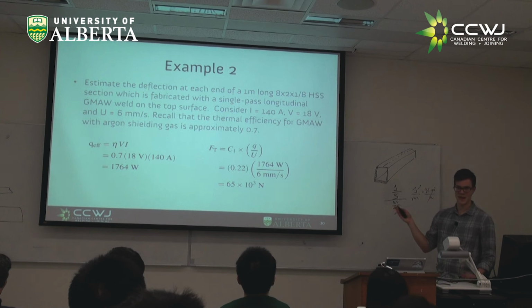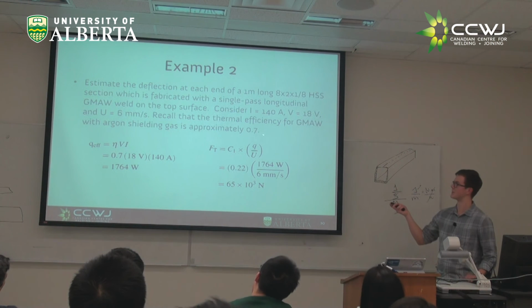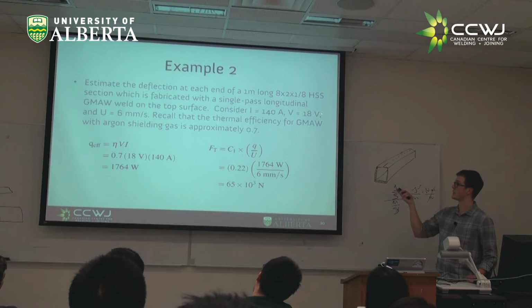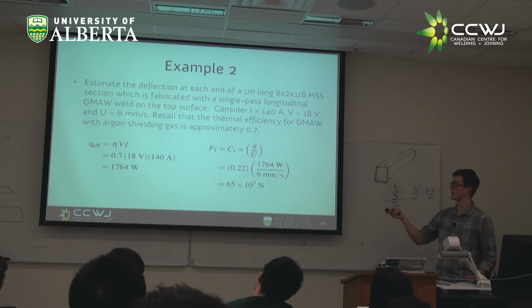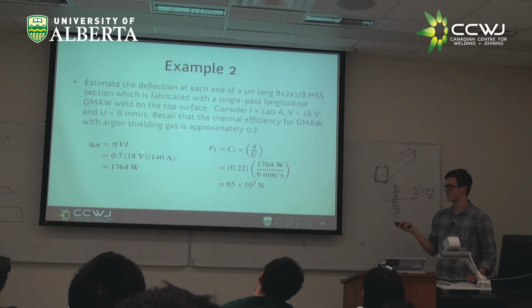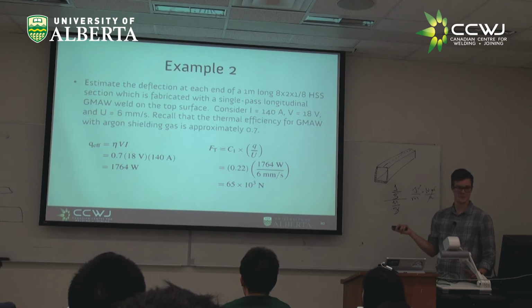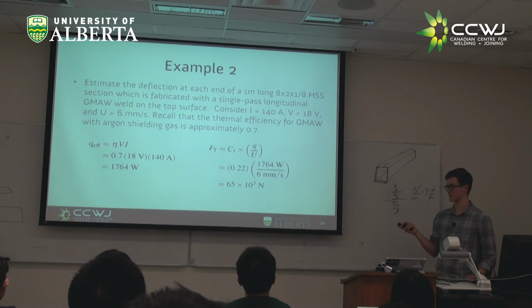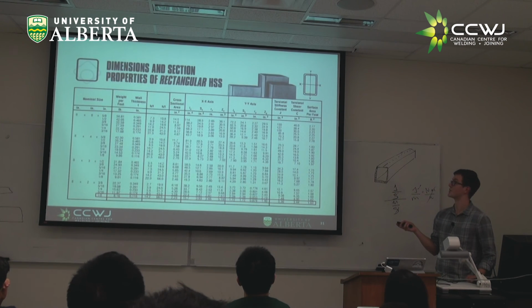So let's start there. This is exactly the same as we did before, except here we've even given you all the parameters in the right units. So current of 140 amps, voltage of 18 volts, travel speed 6 millimeters per second, and we're going to look at GMAW with argon shielding gas, so efficiency of about 0.7. 0.7 times 18 times 140, 1764 watts. We didn't say here, actually I meant to say here, but we're going to consider this as a structural steel. Typically these hollow structural sections are made of a structural grade of steel. Hopefully that shouldn't be surprising because HSS is in the name.